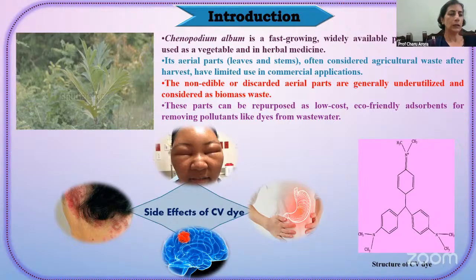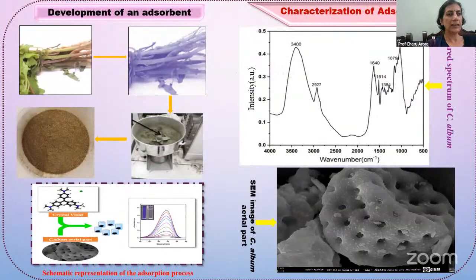Now, the adsorbent was developed by drying the unused part of the plant. After cleaning, it was dried and ground in a mixer. Its powder was sieved to 200 mesh size and it was used as such for removal of dyes. The material was characterized by FTIR and SEM. Here we have shown the FTIR and SEM images.